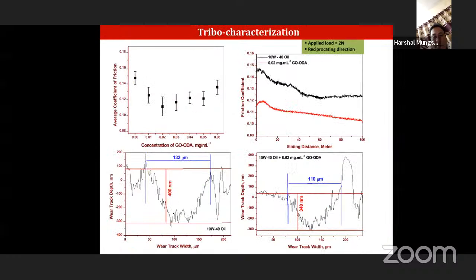And next, tribo characterization. You can see in the case where I use 0.02 milligram per ml of that functionalized material in the lube base oil, there is a significant reduction in the coefficient of friction. In the next graph, if we compare the 10W40 oil and the 0.02 milligram per ml GO-ODA in the presence of this material, you can see in the red line there is significant reduction in the friction.